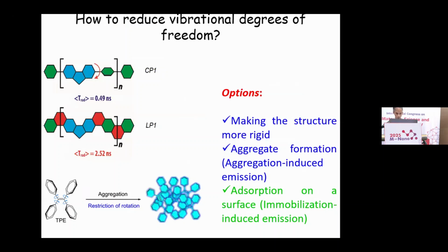So in order to reduce vibrational degrees of freedom, we can design molecules of rigid structure. For example, we can introduce specific moieties between twisted parts of the molecule, and in this way we can change the radiative lifetime of the molecule significantly. Or, for example, we can realize enhanced emission by the so-called aggregation-induced effect, when twisted molecules interact with each other, and in the aggregate the twisting is suppressed, and emission becomes brighter in the aggregate. But I will show you the other method of how we can enhance the emission by adsorption of molecules on the surface of nanoparticles, the so-called immobilization-induced emission.